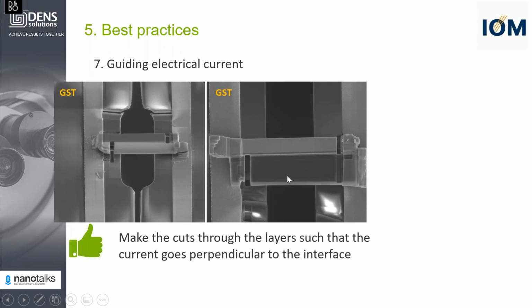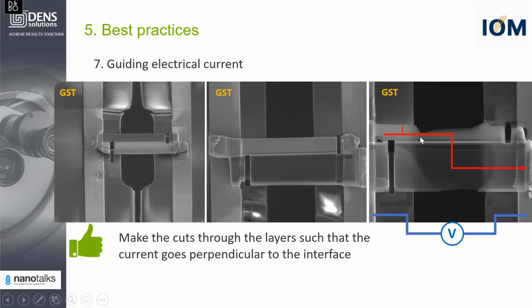And then in this case, the current will go perpendicular to the interface. So if I show another example, we have one cut that cuts through the sample and the bottom electrode, but keeping the top electrode. And then the current will go here, but here we do another cut to prevent current going through the top layer. And we cut the top electrode and a part of the sample, leaving only just the bottom electrode. In this case, when you apply bias, the current goes perpendicular to the interface, and you will see the effect that you want to see.